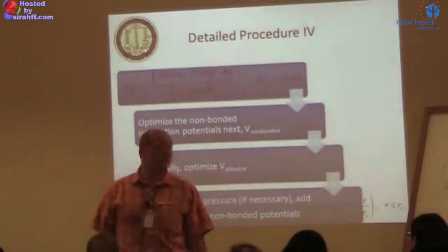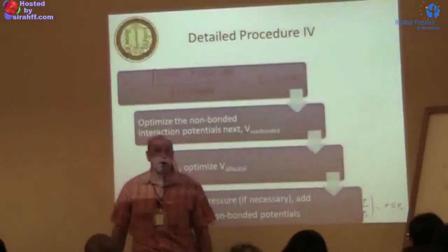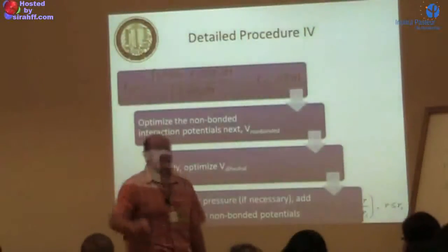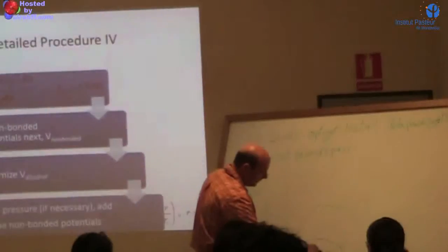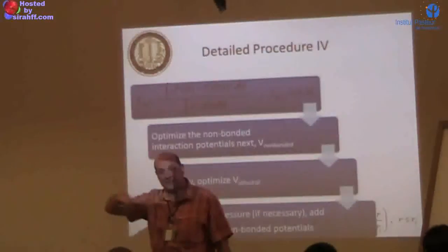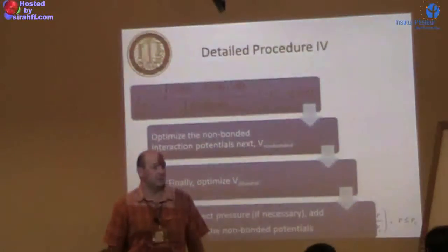The pressure. Typically, you get the pressure a bit off. With a bit, I mean plus or minus half a bar. You may know that in certain simulations that's not that bad. What you then typically do at the long range part, which is almost zero, is add a very slightly attractive part, which, if you integrate that, leads to a correct pressure. So you add this pressure correction, which is typically some prefactor times 1 minus r over rc, a slightly linear potential, which is a constant force, and that constant force obviously then leads to a decrease in pressure.